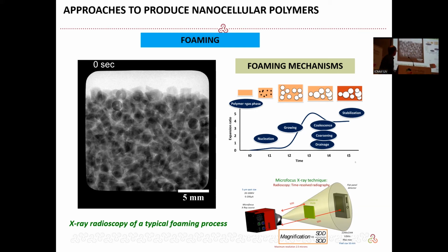And during foaming, there are many things that occur. First, we have nucleation of the cells. The cells are created. Then growing of the cells. And during growing, the expansion ratio increases, so the material expands. And then we have the degeneration. You see now the cells are disappearing. So we have coalescence, coarsening, drainage. Finally, we need to stabilize the material. So foaming is something tricky. There are many physical-chemical phenomena that take place during this kind of process.